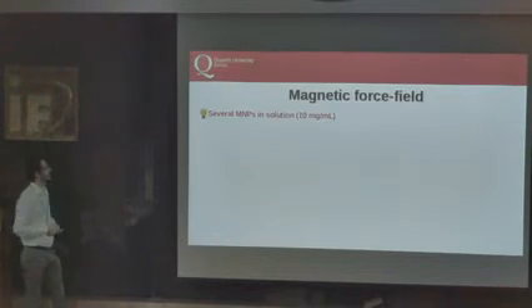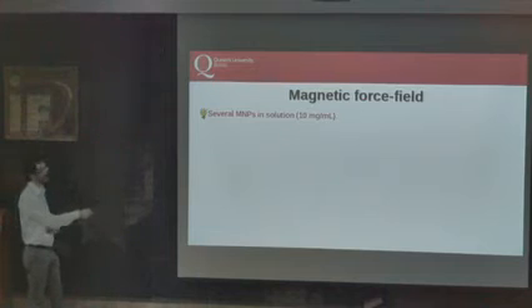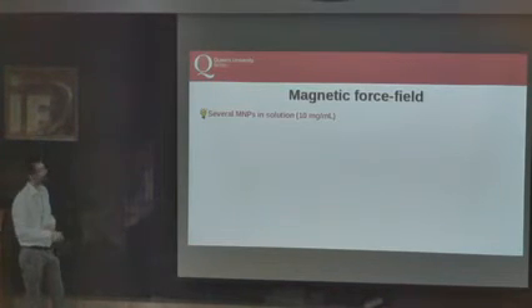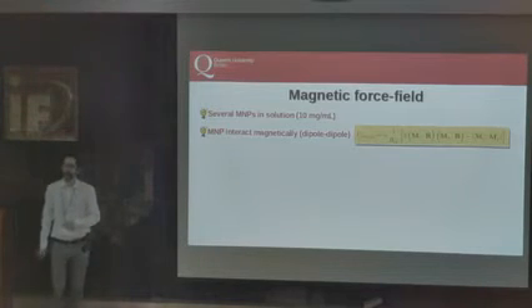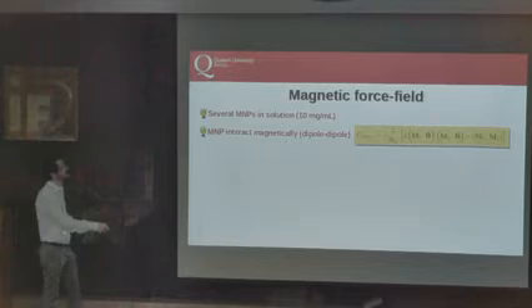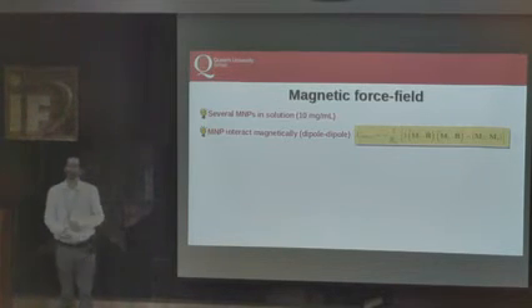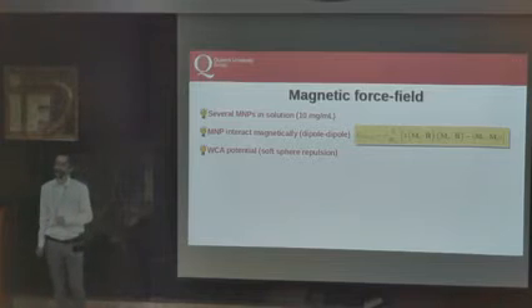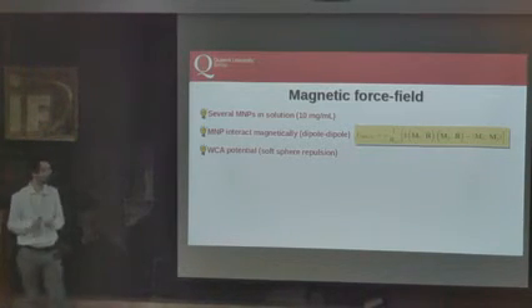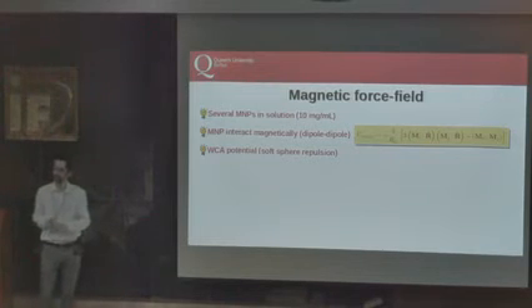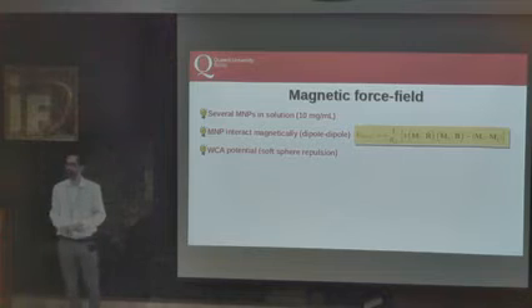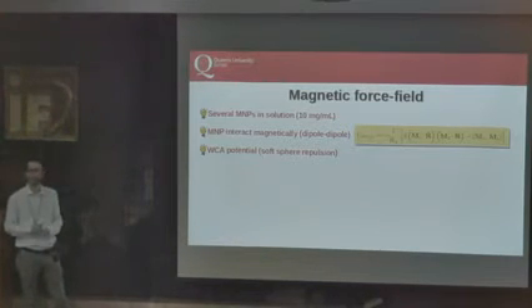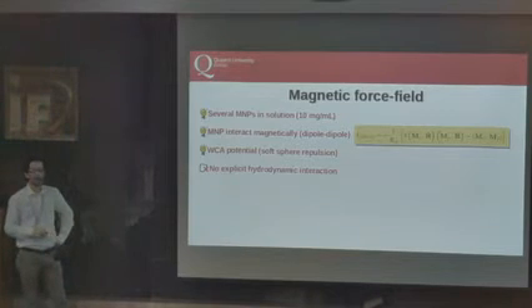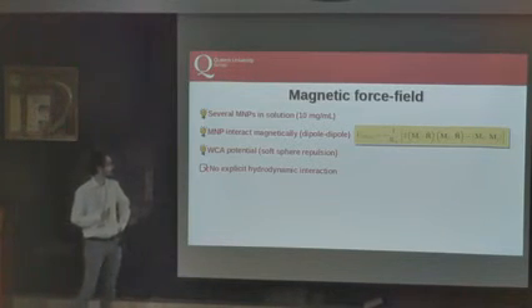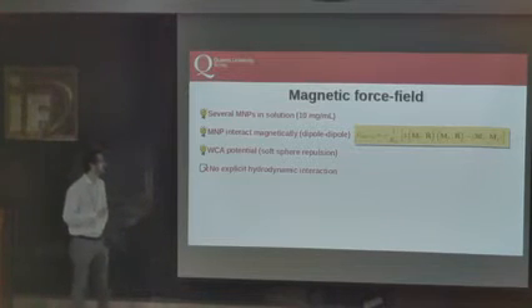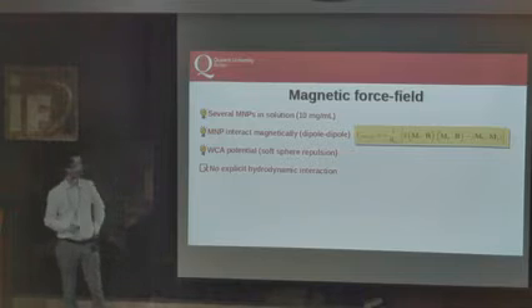But first of all, we have several magnetic nanoparticles in solution. This is the concentration I was referring to before. We know what the dipole-dipole interaction is. So it's missing a ratio here. And as I said, as we use the simplest soft sphere repulsion, the only long-range interaction is the dipole-dipole interaction in this case, just to simplify the analysis of our results. And in these calculations, because of the tiny, small vial, we have neglected all the hydrodynamic interaction.